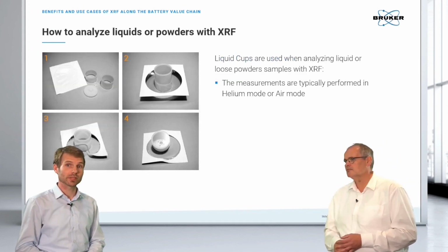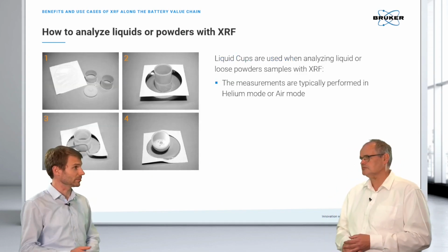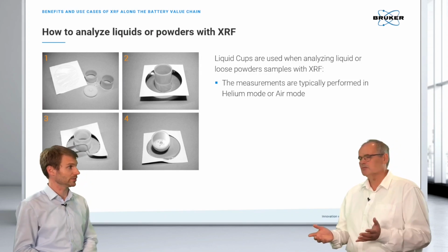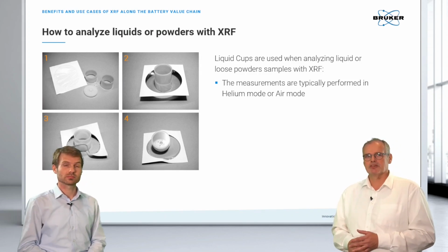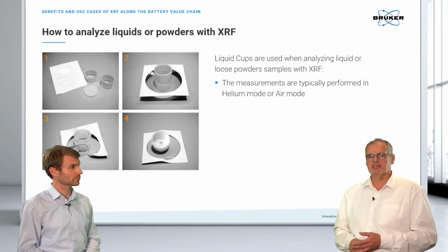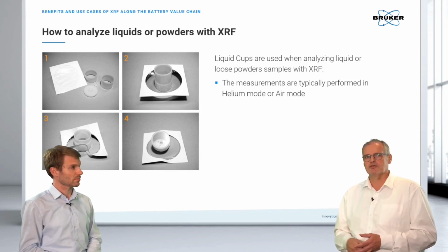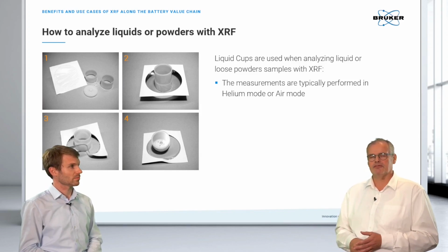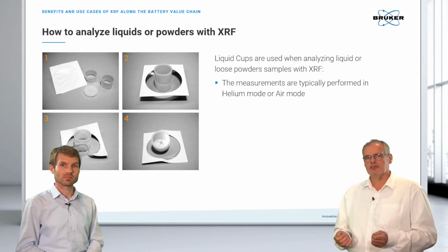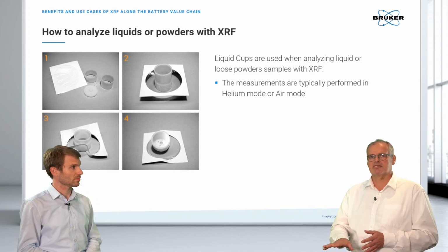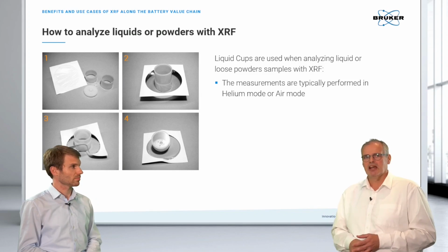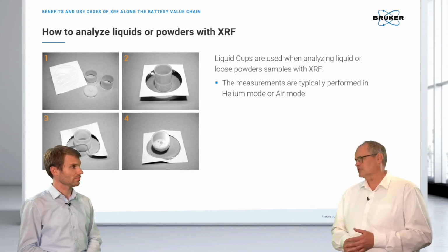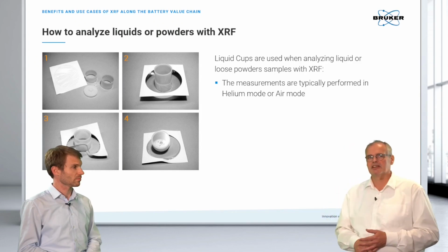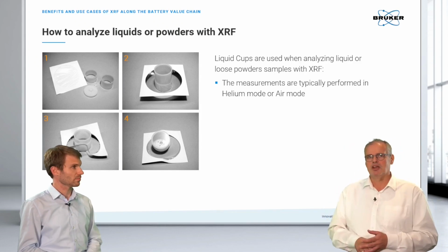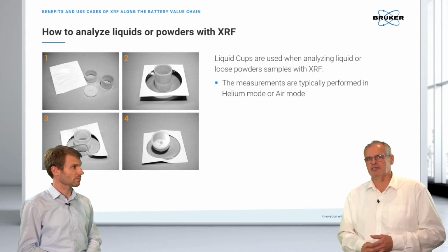However, the simplest way remains the liquid cup and loose powder analysis. The liquid cup is pretty easy to assemble. You see here the four pictures. You have two plastic rings. You have the foil in a paper frame. You put the foil between the two rings and press the top ring slowly down. After you have filled the cup, you can close it with a plastic cover.